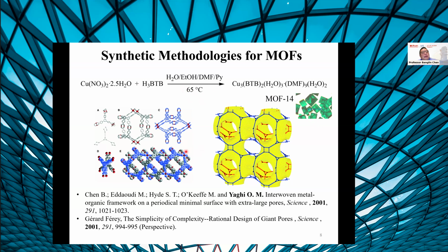Secondly, this work means that we can use quite a large organic linker. We are still able to construct a MOF material with very large pore space that is still stable. And also, from the earlier copper ATC, MOF-11, and this MOF-14, it shows that under certain conditions, if we can generate this paddlewheel cluster and different organic linker shapes, basically the structure topology is predictable. And nowadays we call it reticular chemistry.